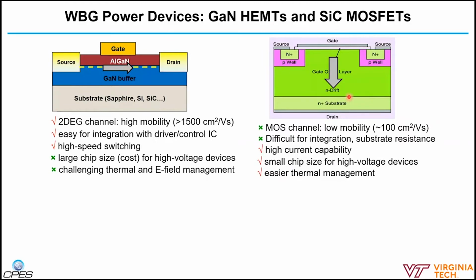The silicon carbide power MOSFET is a vertical device, and it uses an inversion type MOS channel. The mobility is relatively low, and the vertical device is not very suitable for integration. But it allows much more spreading of the current and also the electric field. So it favors high current, and if we want to make high voltage devices, we simply need to make the drift region much thicker and lower doped. The die size can still remain very small. Also, due to the more spread out electric field and current distribution, the thermal management is typically easier.